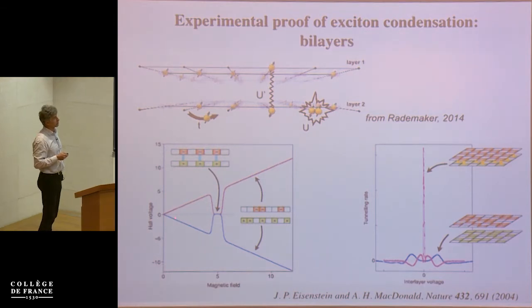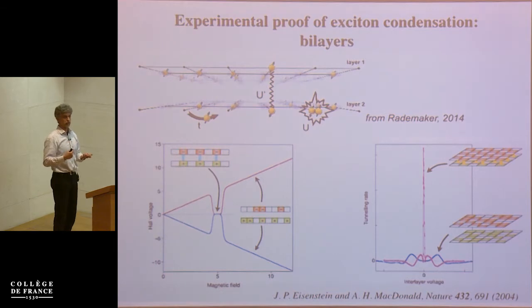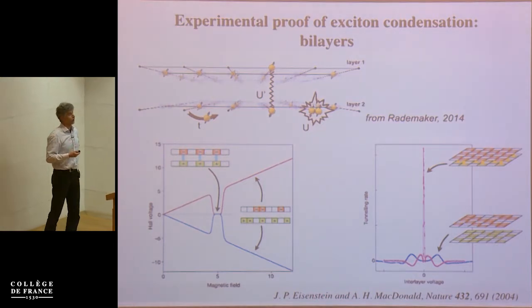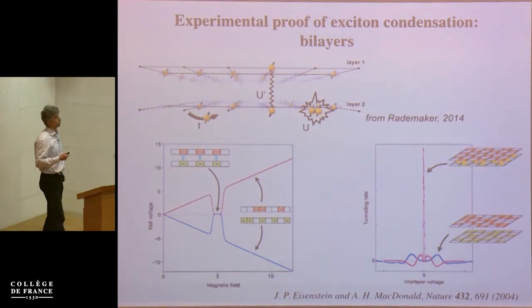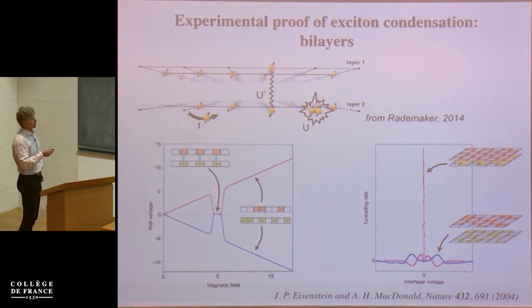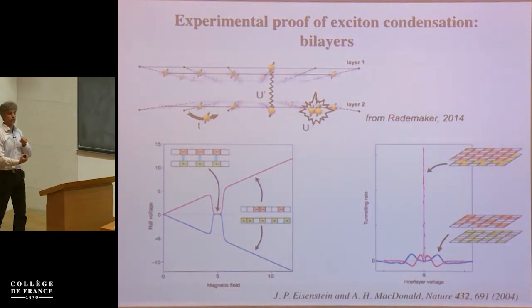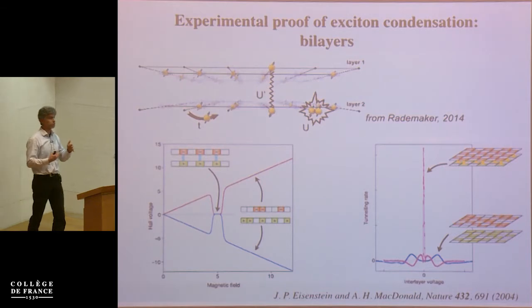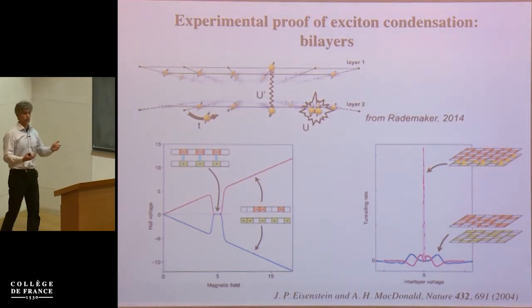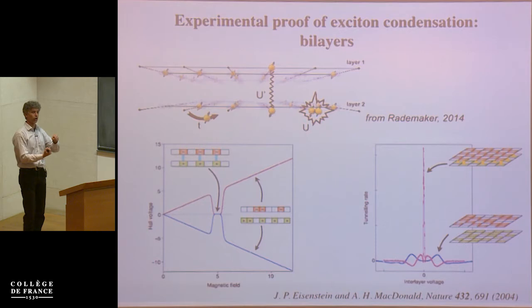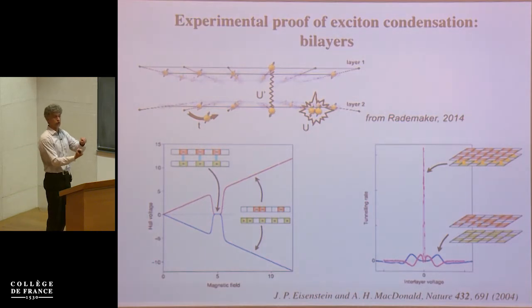And what they measured was Hall conductivity. So they were changing the magnetic field, and by changing the magnetic field, they were tuning the electron and hole concentration in these two layers. So you observe that in one layer you have electron-like Hall conductivity, and in the other layer you have hole-like Hall conductivity. And if they got to a rather narrow region where the concentration of holes and electrons were approximately equal, the signal went away, which was a signature of these electrons and holes forming a neutral bound pair.